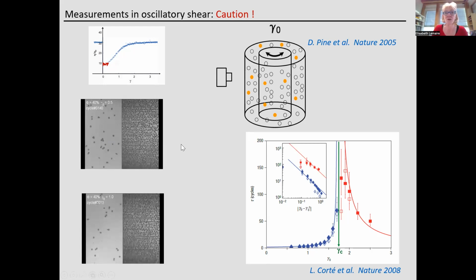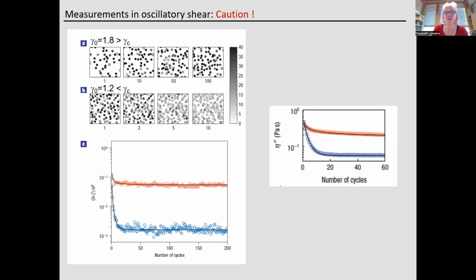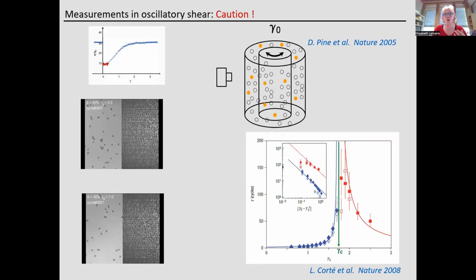But what is important is that to reach this steady state, for instance, for an oscillation at low amplitude, the suspension passes from a suspension where the particles experience contacts between them, to a suspension where the particles have moved in order to avoid these contacts. This steady state is named a super-absorbing state.